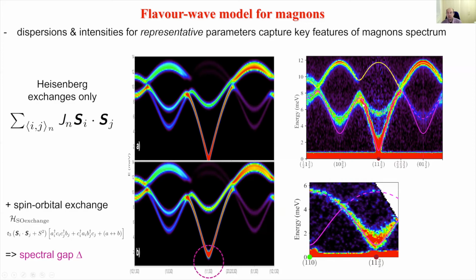For example, here, this is the experimental data, and this is the calculation for the magnons. So we have the linearly dispersive strong mode here, and all the key features are really reproduced. There's a gap mode here that's weaker in intensity than that one. There are two modes here, where both carry intensity. Here, only one carries intensity. We think these are fine details that potentially could be remedied by doing a full fit of this. Now, the important part is that if we add a spin-orbital exchange, then the dispersions are essentially unchanged at high energies compared to before, but a gap appears,